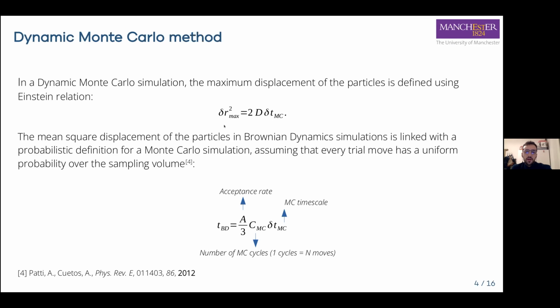square displacement computed in Monte Carlo simulation, which will depend on the acceptance rate, to the mean square displacement commonly computed from Brownian dynamics simulation. So at the end, we can recover a unique time scale for our Monte Carlo simulation that will depend on the Monte Carlo time scale that we set at the beginning, the number of trials that we perform, where we define one Monte Carlo cycle as N trial moves, so N random rotations and translations of particles, and the acceptance rate, which is the percentage of trials accepted over the total trials attempted.